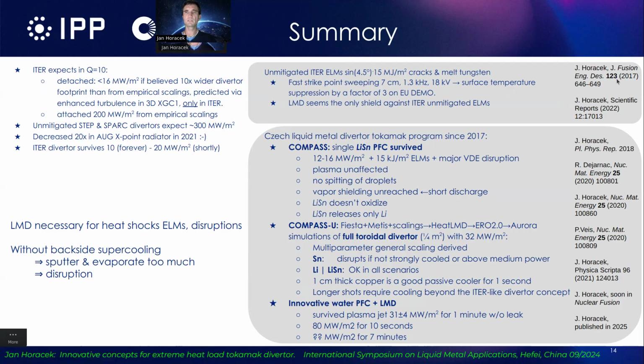So that's why we developed this liquid metal program, which is published in these papers, where we did experiments on COMPASS, then do simulations on COMPASS Upgrade, which I'm just now publishing in Nuclear Fusion. And I see that the heat fluxes in medium power H-mode will be about 32 megawatt per square meter in attached plasma. So we can achieve these power densities on our medium-sized tokamak in Prague, Czech Republic, and test new technologies.